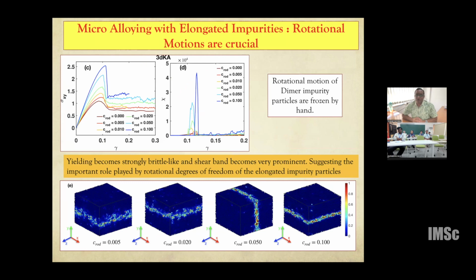So then, just for the sake of theoretical curiosity, what the student did was he stopped the rotational degrees of freedom of these dimers. So the dimers in the simulation can no longer rotate. They are frozen by hand. If you do it and then look at the same stress strain curve, we see that the stress strain curve becomes very different. Now the yielding becomes extremely sharp, which is signaled by the susceptibility. The susceptibility peak went up by at least a factor of 10 to the 4, which is huge,